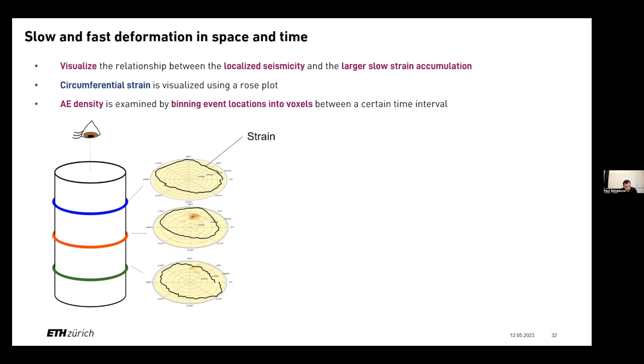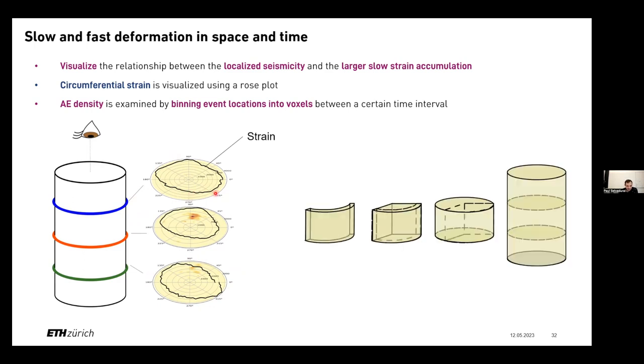Another one is just to visualize. It's not an easy topic to plot. The previous slide showed strain rate from this map view, but this is a three-dimensional problem in our case. And we also have localized seismicity and deformation happening in 3D. So what you're seeing here is we're looking down at the top of the sample in map view, where we have rose plots, and the strain in each of the top, middle, and bottom will be presented as these black rose plots here. And the density of AEs will subdivide the volume into voxels and populate for each segment the number of AEs that occurred in that voxel, because due to spatial constraints it should have some influence, or it might be related to the observations we're seeing in the global deformation using the fiber optics.